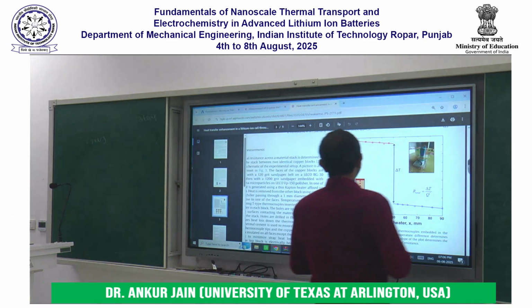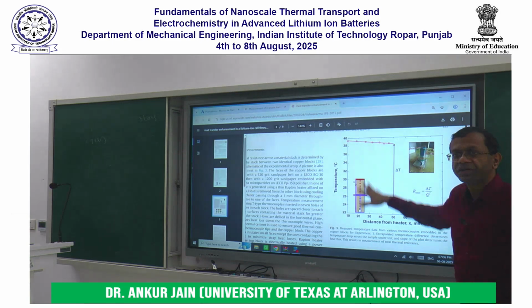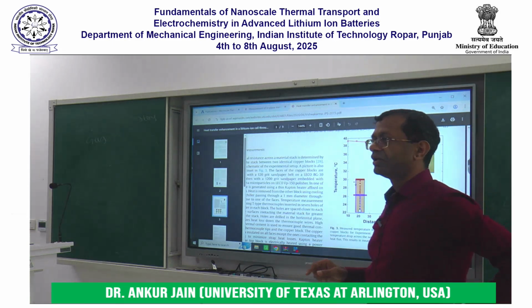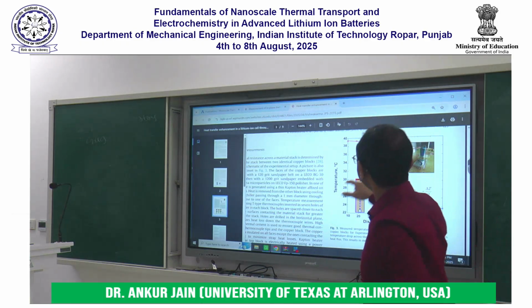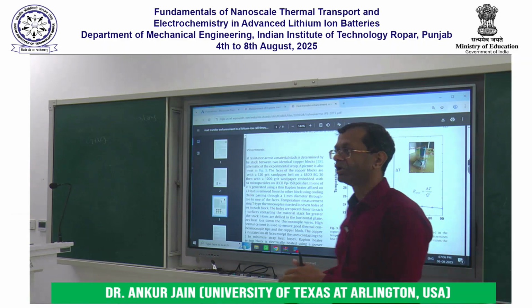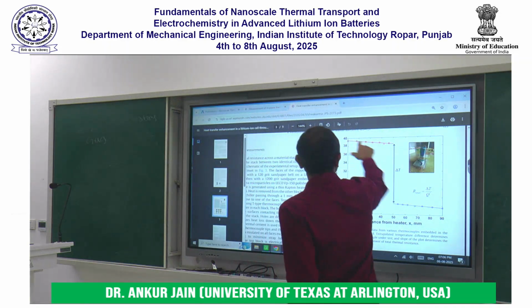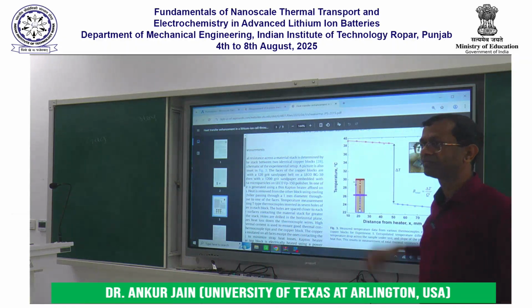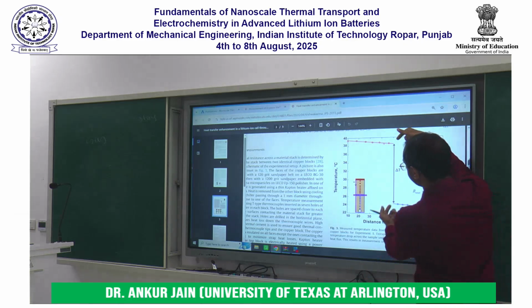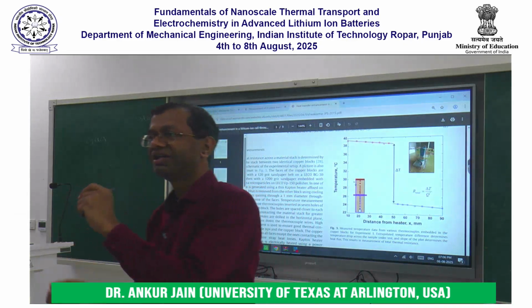Alright, so what does this give us? This tells us a few things. Firstly, the temperature distribution in each of these blocks by themselves, either the red or the blue, is very linear, right? I'm able to fit it very nicely with straight lines in both of them. However, interestingly, there is a large temperature jump. There is a large temperature jump at the interface.